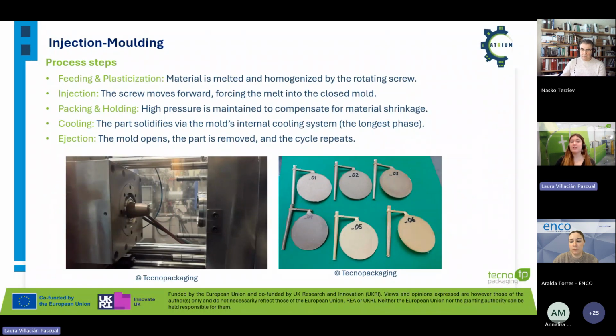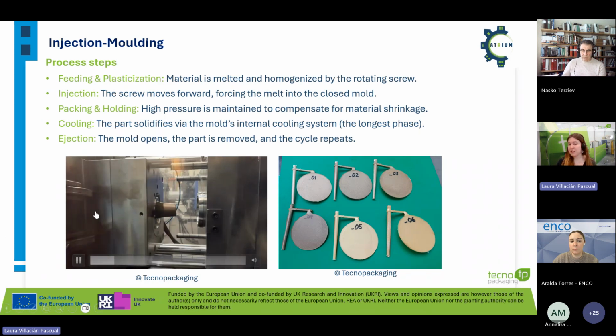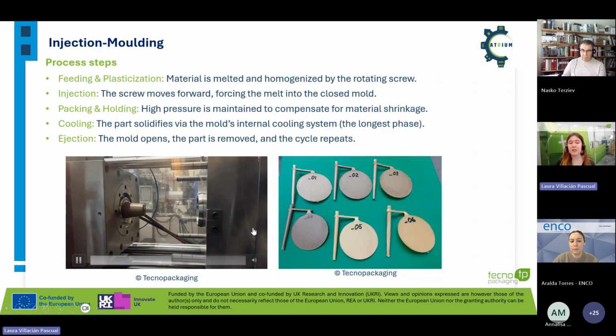The process steps include the feeding and the plastification. So the material is melted as well as in the extrusion compounding, but with a smaller screw in this case. And afterwards, it is injected. The screw moves forward, forcing the melt into the mold, and then high pressure is maintained in order to compensate the material shrinkage. This is also important for biopolymers. Afterwards, as you can see here in the video, it is pressed and cooled down, and then you have the ejection. That is what you are seeing in the video.